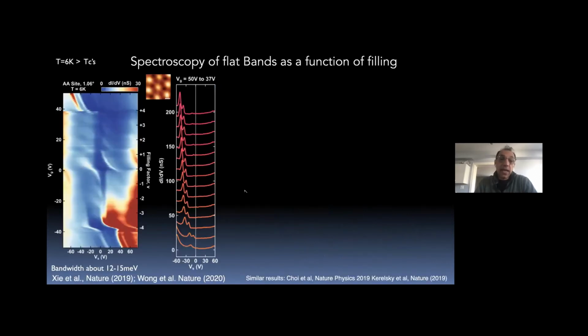Now, what happens next as you go into the partial occupation of the flat band, where the insulating and the superconducting phase arises, is very interesting in the spectroscopy. What you see here are the two sharp peaks that I showed you, and what we're doing is changing the gate voltage. You see that this peak is moving towards the chemical potential, and it remains sharp for some time. But as it approaches the chemical potential, you can start to see that it becomes very blurry. You can of course see that also in the panel on the left, where the gate voltage is the y-axis, the tip-sample bias is the x-axis, and the color scale represents the density of states.